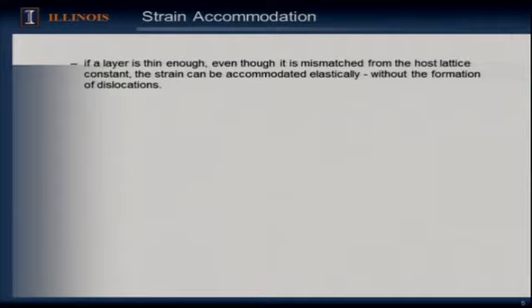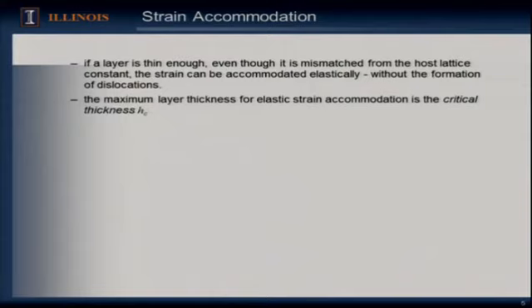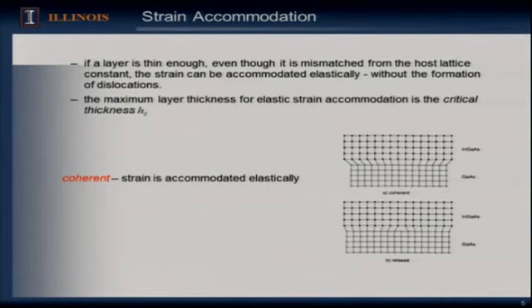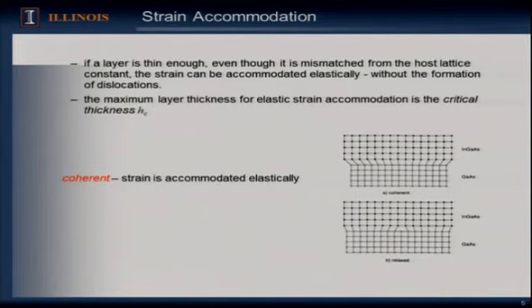If the layer is mismatched, the strain can be accommodated elastically within the limits of the material without the formation of dislocations, if the layer is thin enough. The maximum layer thickness for this elastic strain accommodation is called the critical thickness. The timing is important: this work coincides with when quantum wells and really thin layers are becoming practically available. If you can make the layer thin enough, it can be stretched and pushed so that strain is accommodated elastically; if not, it will relax by forming misfit dislocations, which then propagate through the material — very undesirable for an optical device.